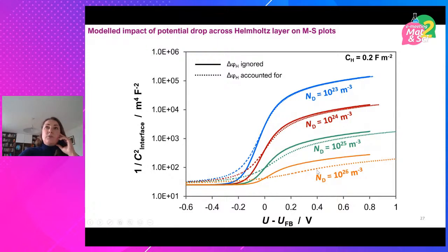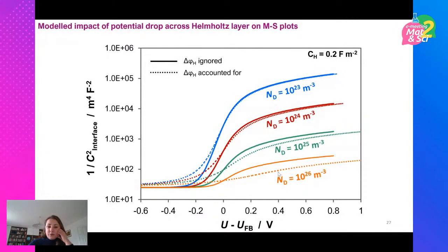So what it shows is that when you look at your experimentally determined Mott-Schottky plot, you are, without modeling, unable to distinguish how that plot is impacted by the potential distribution across the semiconductor and the Helmholtz layer, and how much the Helmholtz capacitance contributes. So the latter can be accounted for, but the stretch across the x-axis is very difficult to do without a model. So that's the story with the Mott-Schottky plots.